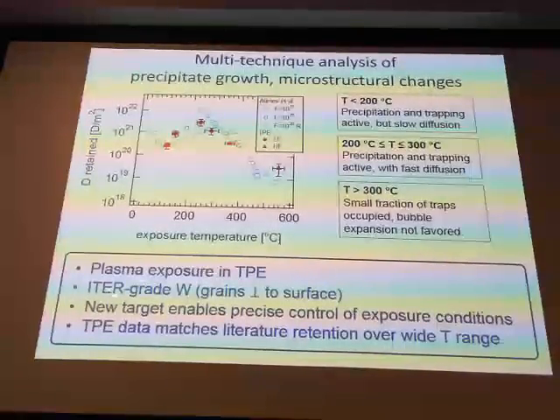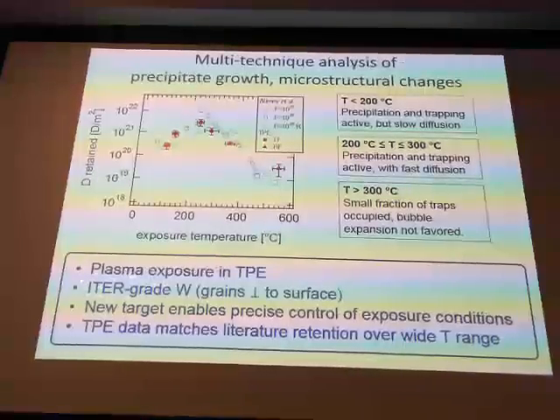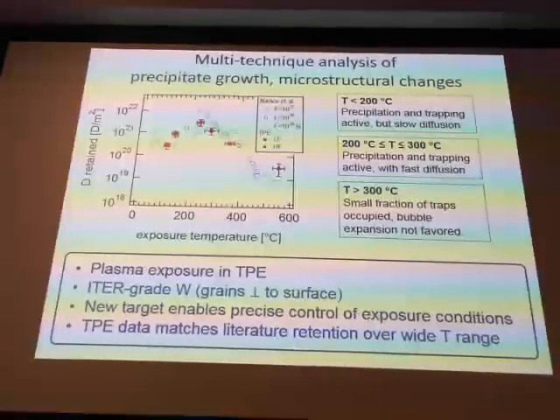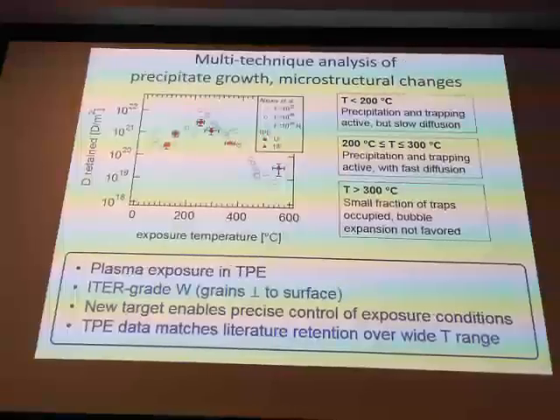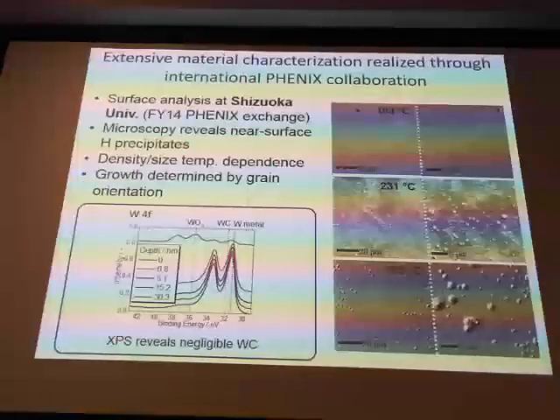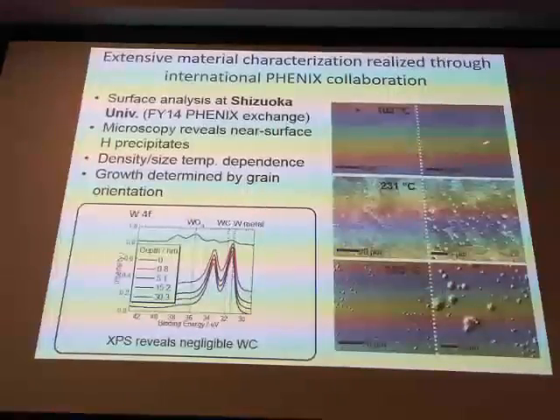So we investigated this with the tritium plasma experiment. We wanted to look at this precipitation effect in more detail. And so we looked at the same material that will be used in ITER, this ITER grade tungsten. And this tungsten material has grains perpendicular to the surface to promote heat transport away from the plasma-facing surface. And so we looked at these samples.